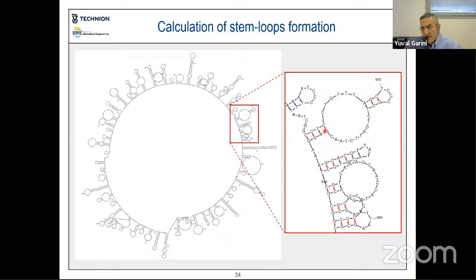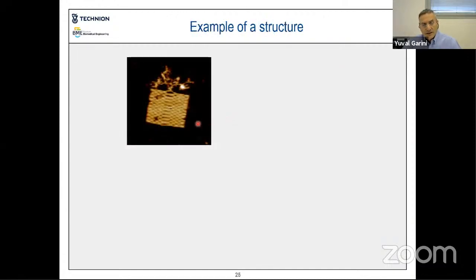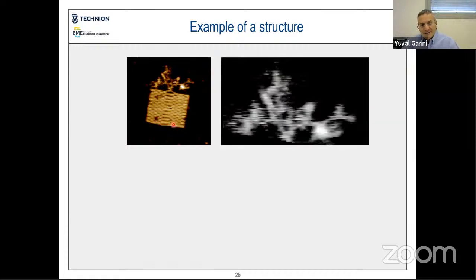For some of them, it's clear why they are formed. And you can see that, roughly speaking, there's more or less 50% of the DNA that take part in it. So it must be taken into account for the calculation. You can see here as an example, one of the structures. You can actually see, even from the picture, that the structure is quite nicely designed. There are some missing points along the structure, but that happens.